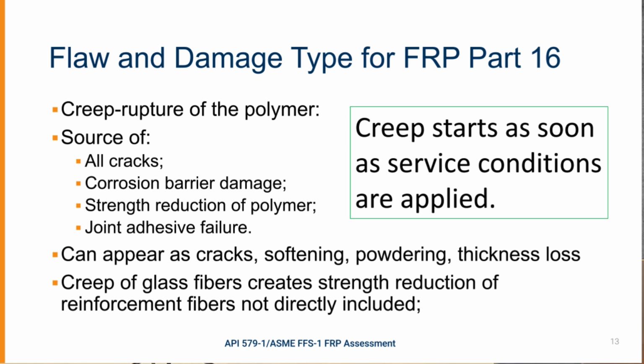So as soon as you put FRP into service, it starts to creep. We start to see changes to the materials and the material's strength as a consequence. This can appear as cracks, softening, powdering, thickness loss. The creep of glass fibers also occurs, and it creates a strength reduction of the reinforcement fibers. But this is not directly included.